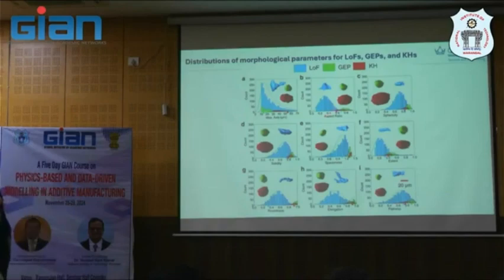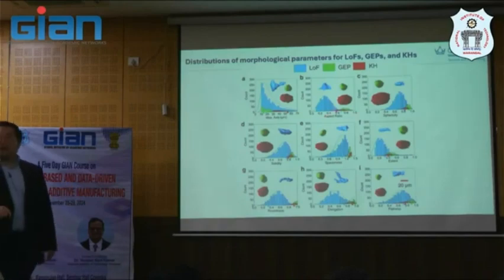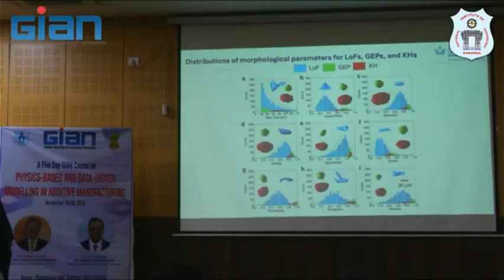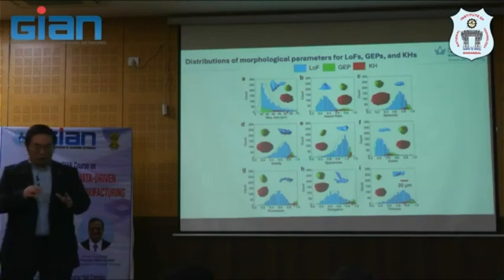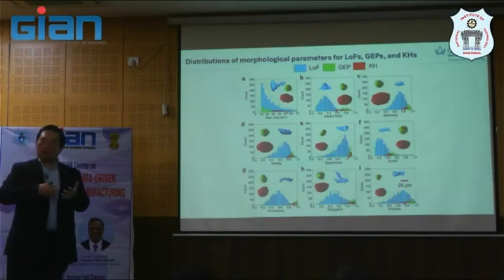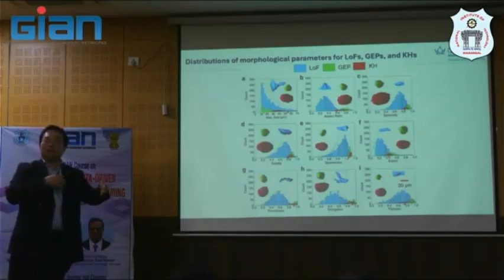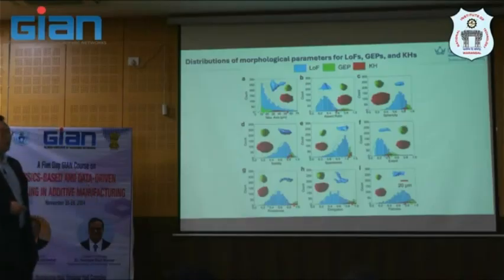Then you see the dominant porosity is actually lack of fusion, in the blue and light blue here. There is a lot of lack of fusion porosity. Keyhole is quite minimal in the samples that they investigated, these 9 samples. And then there is an intermediate, which is the gas entrapment porosity here. So this paper is quite interesting and shows a good way to do data-driven work with data from XCT, which is experiment. So it's heavily coupled between experiment and coding.